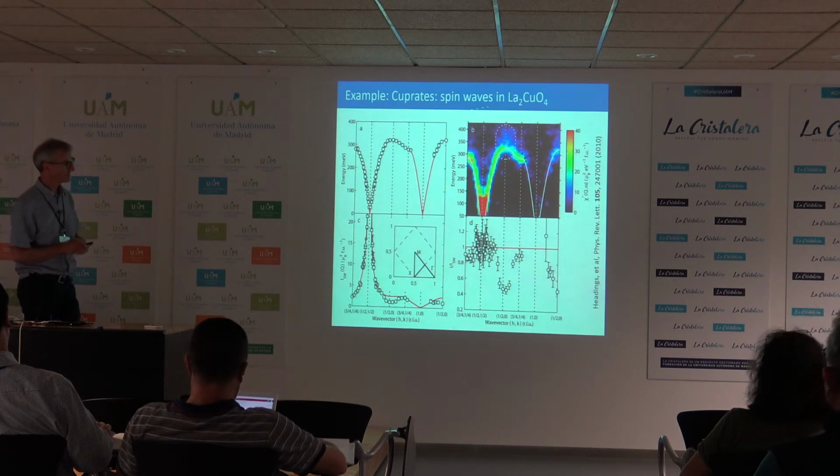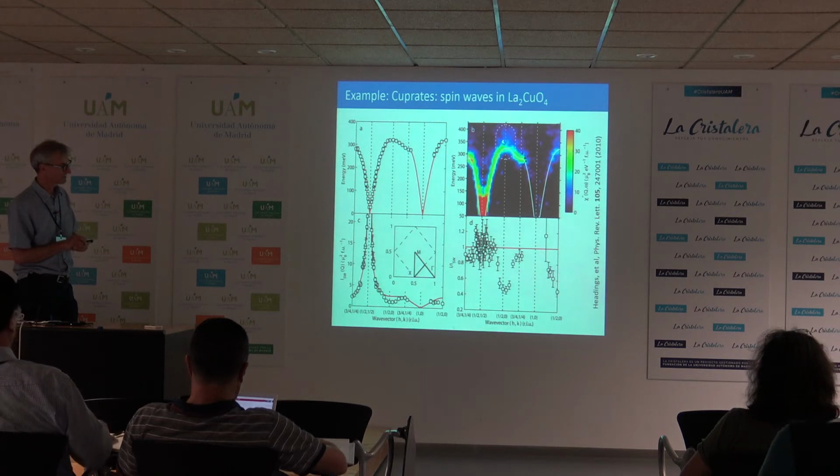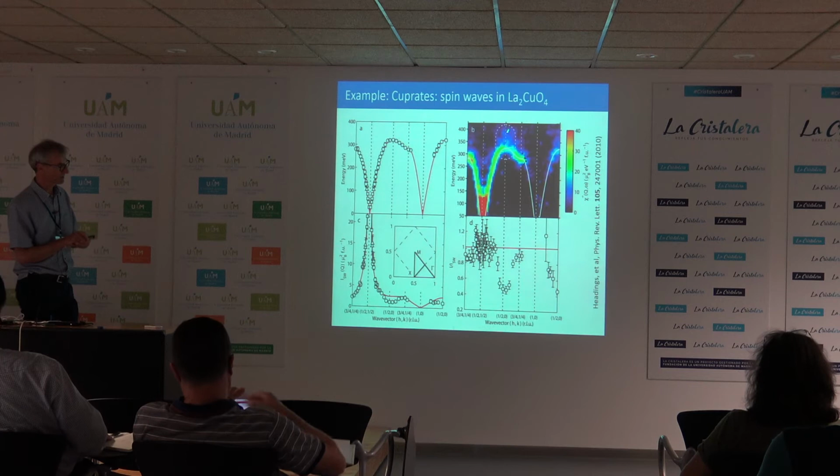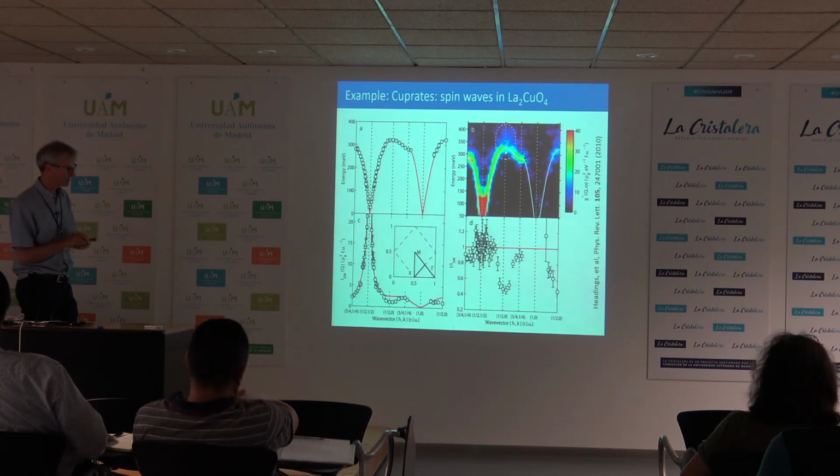But what we find in lanthanum cuprate, and you can see this diagram here, at the half-zero position, is that the excitations are very strongly damped. This lighter blue colour here, compared to, say, here, we see this extra scattering above the spin wave, showing that the spin wave is damped, or it's almost falling apart.